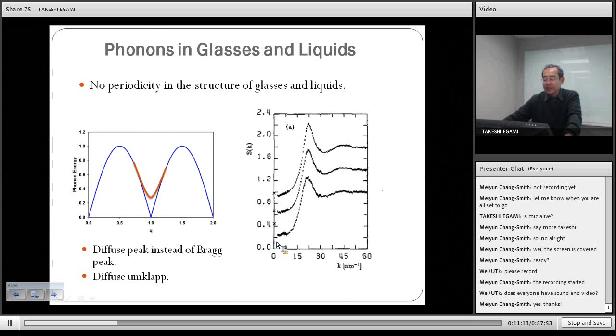So what happens is that if you take a diffraction pattern, instead of Bragg peaks, you have a broad diffuse peak like that. So this is the diffraction S of Q from liquid helium. Here, this corresponds to the first Bragg peak. So that represents kind of interatomic distances. And instead of a Bragg peak, we have a broad peak. If you have a Bragg peak, this phonon, as I explained last time, comes down to 0 because 1,0,0 is physically the same as 0,0,0. These are gamma points. So physically they are the same.